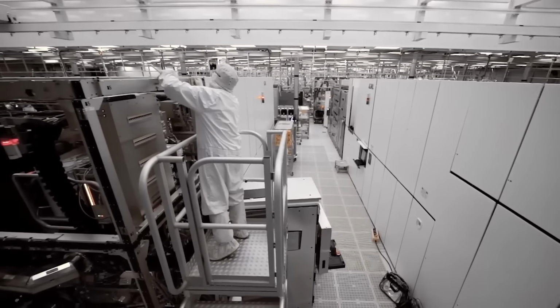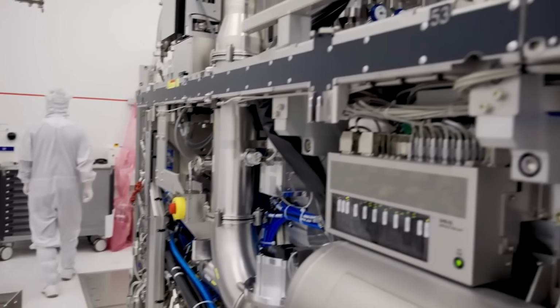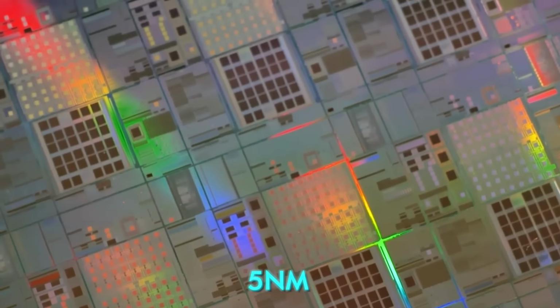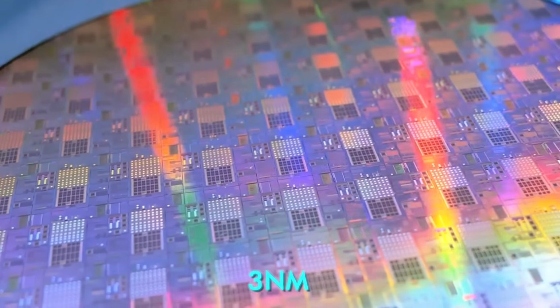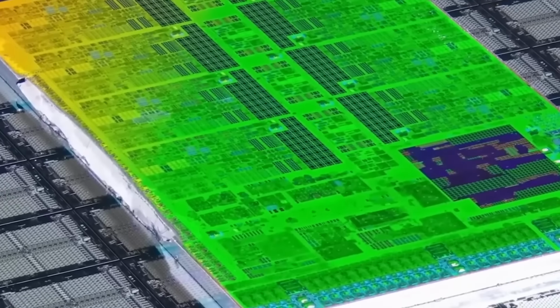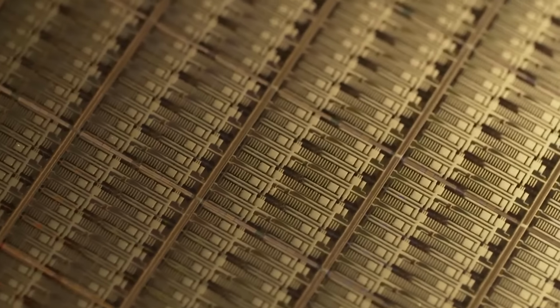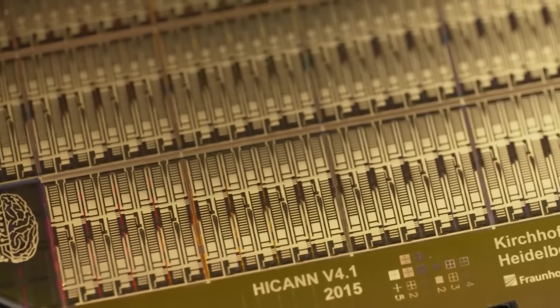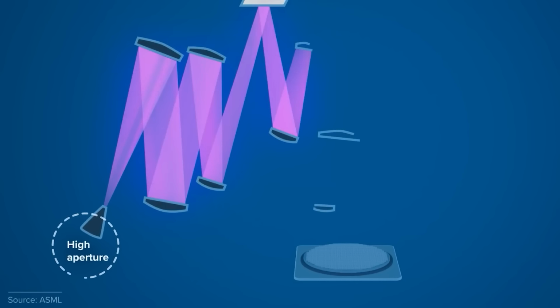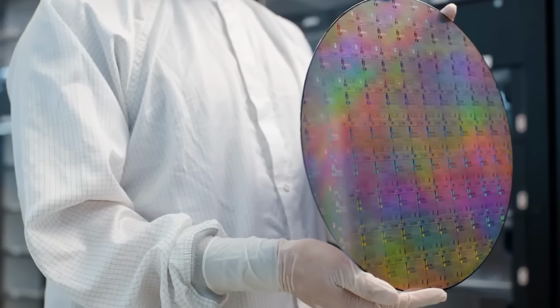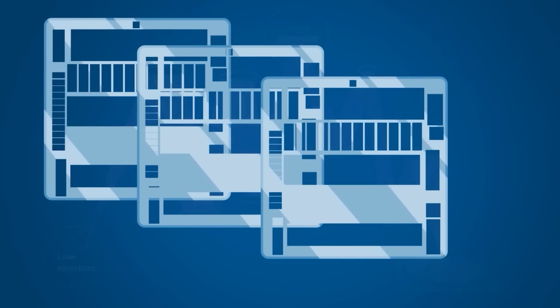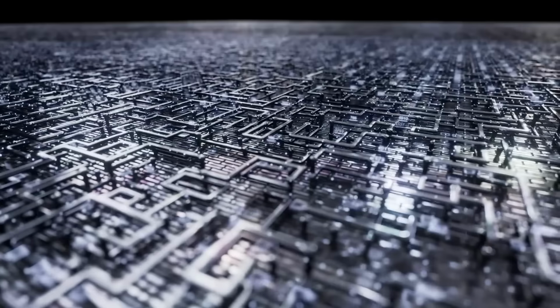Now, standard EUV has been in high volume production since around 2019, and it genuinely changed the game, but as nodes push below 5 nanometers, and certainly below 3 nanometers, even EUV is starting to show cracks. The main issue is stochastic noise. EUV uses photons to expose a resist on the wafer, and at these scales, the number of photons hitting any given spot is actually quite small. Photons behave randomly. Small fluctuations in how they land create variations in the edges of the printed features, which is called edge roughness. At 2 nanometers and below, that roughness becomes a real reliability problem. Transistors do not switch cleanly, yields drop, and then there are also defects from the tin plasma process itself.